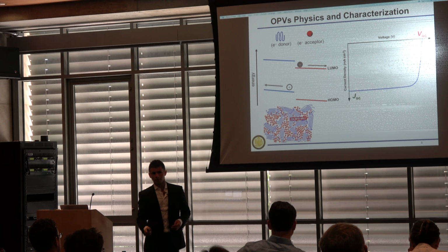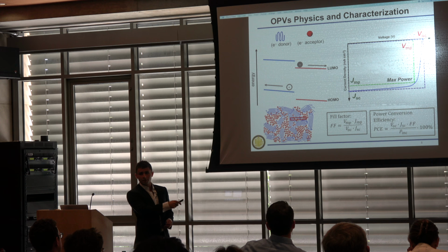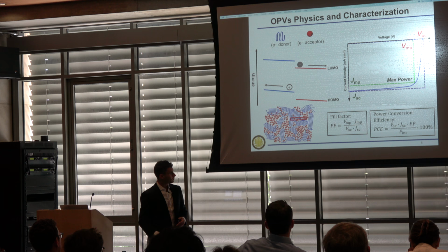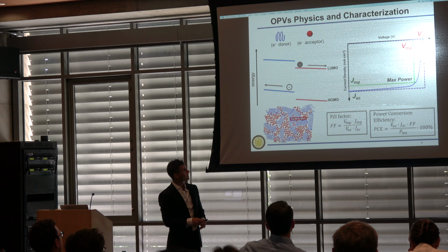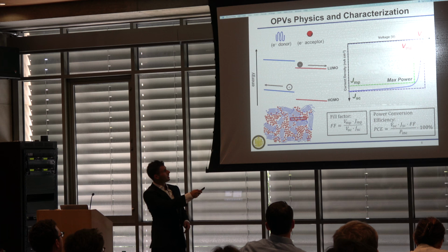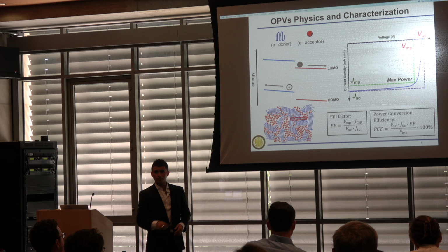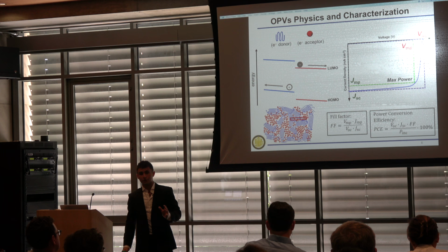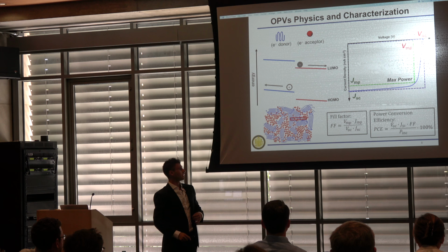So the maximum power point will be where the product of the current density and the voltage are maximized, are the highest. A convenient metric that we use actually to measure the square-like shape of this curve is called the fill factor. And you would arrive at this by taking the ratio of the max power point power over the product of the VOC and the JSC. And then we use this oftentimes to calculate the power conversion efficiency. So take the open circuit voltage multiplied by the short circuit current density, and then times the fill factor.